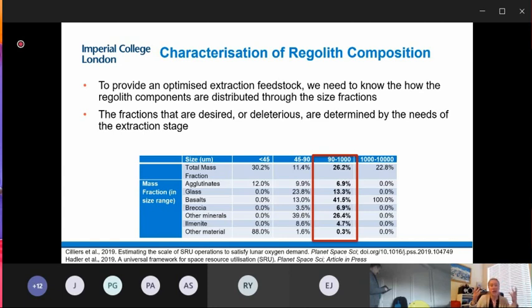But anyway, if we took, for example, a sample of regolith and split the components up by size, perhaps we would like to focus on the 90 to 1,000 micron fraction. And we can see from this table that that is about 26% of the total mass. So 26% of the mass of this sample that we have binned in this way is in the right size fraction. And it has an ilmenite content of 4.7%. What does that do to the scale of our process?